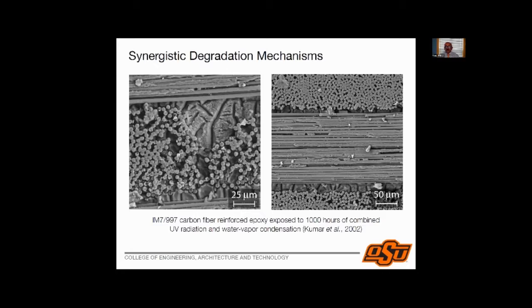These are two images from composite laminates, and what you can see is that we are losing the epoxy. So these are the carbon fibers that you see. These are carbon fibers coming out of the plane of the screen, and if you look over here, you see carbon fibers running across the screen. So on the top, you would have one layer. This is a 90-degree layer over here. Then you'll have another 0-degree layer. And if you zoom out a little bit, then you see the image on the right. It's the same thing. So what we found was that when both these environments act at the same time, we actually get physical removal of the epoxy.